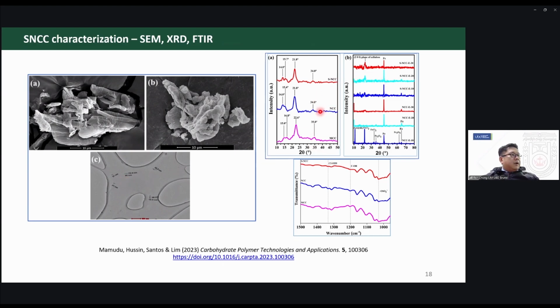Here again we have the XRD. This one on the left is the XRD of our microcrystalline cellulose, nanocellulose, and sulfated nanocellulose, just to show that there are some crystalline structures in them. On the right here is the XRD of the coated sample.